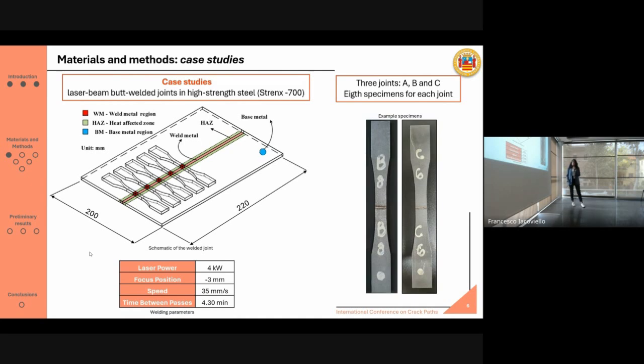From each joint, 8 specimens were cut out. 7 specimens were used for the experimental test, while 1 specimen was used for the metallographic analysis. And here you can see example pictures of 2 specimens extracted from joint B and joint C. Concerning the first phase, the reverse engineering phase,